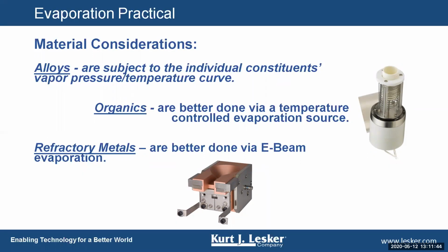Does the pellet size affect the deposition rate and uniformity for sublimating materials? It will. And the reason, look at it this way. I try to get as dense a material packing as possible, and that helps me with the thermal conductivity issues. Generally, as a rule, the smaller the pieces, the better, as far as I'm concerned.